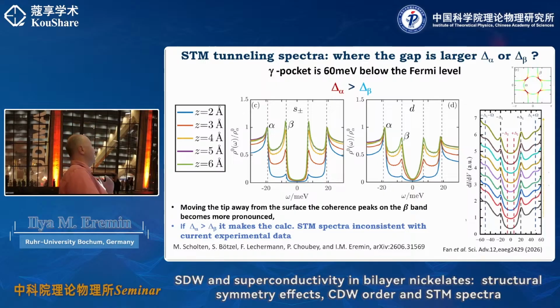But even more, since in the STM they see two gaps, this is the data of the Hoffman group. Now let's assume for a moment that the gamma pocket doesn't cross the Fermi level. Then you have two possibilities for where the main gap is. You can start from the situation that the larger gap is in the alpha pocket and the smaller gap is on the beta pocket. Then you run the simulation as a function of z, the tip height. And you find an interesting situation: it's very hard to reproduce the experiment, because you start when the tip is very close and then you see this one.